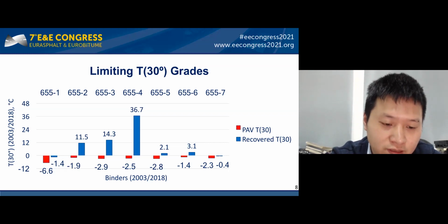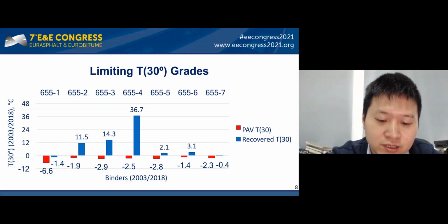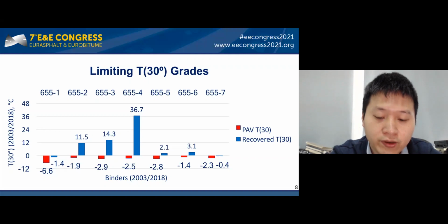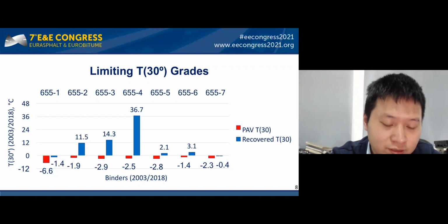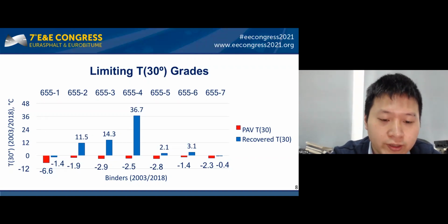For this set of binders, though, we can see that the PAV residues are again falling in a rather narrow range, while the recovered binders are more in agreement with field performance. However, sections 1 and 7 grade similarly, which is not in agreement with their field performance, so there is more to the story.